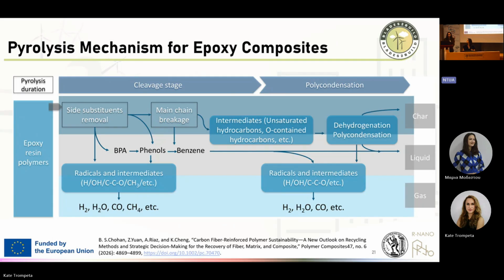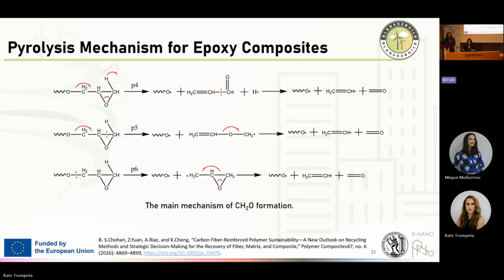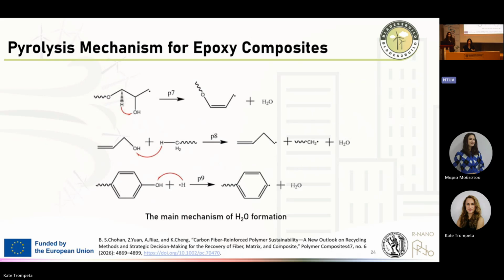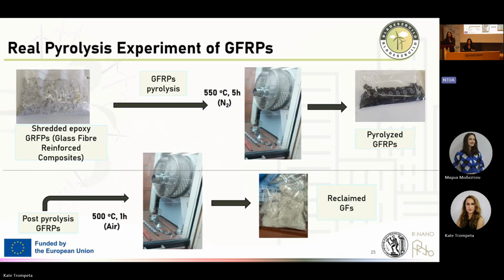So what happens when we have an epoxy resin inside the pyrolysis furnace? We have two main stages, the cleavage stage and the polycondensation. Several reactions take place, radicals and intermediates are produced, and the main breakage results in, for example, carbon monoxide, water, hydrogen, and also as byproducts char, liquid, and gas emissions. We have carbon dioxide formation, formaldehyde formation, and also water. So these are emissions that need to be measured in these experiments to have the mass balance and to know what type of emissions occur from these types of processes.